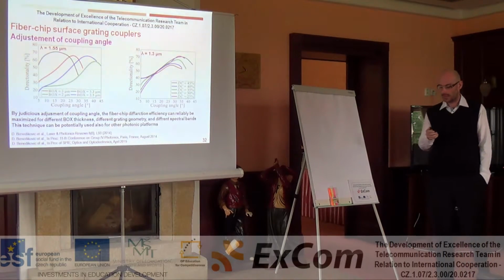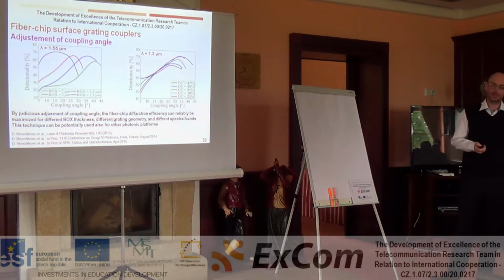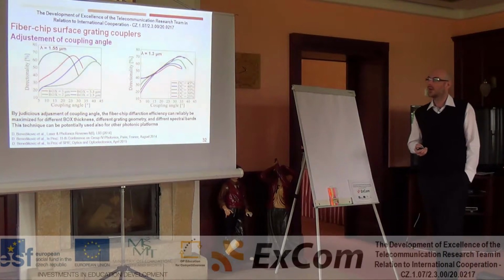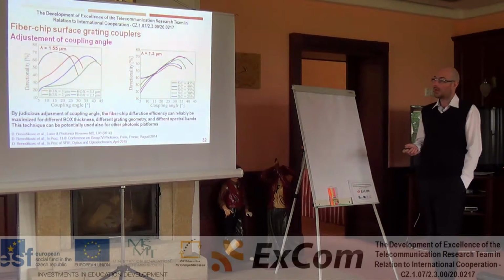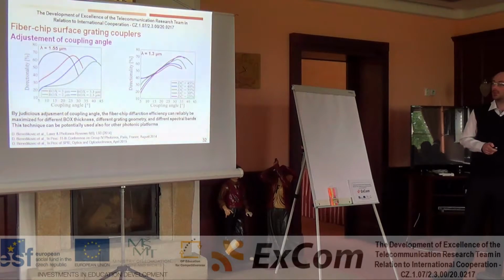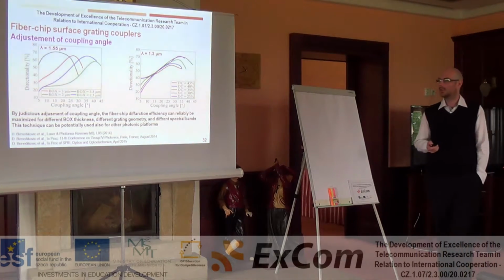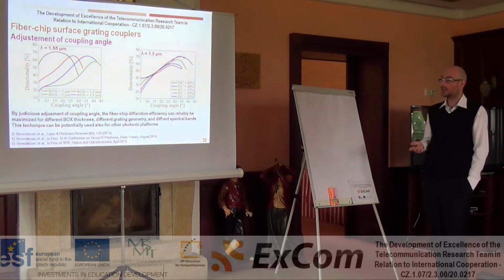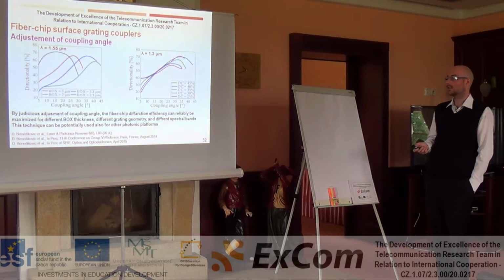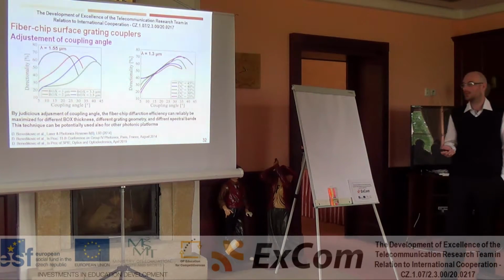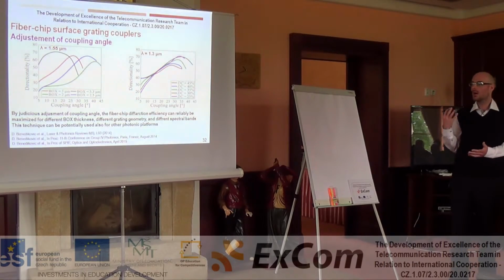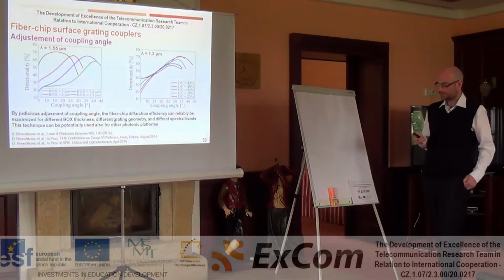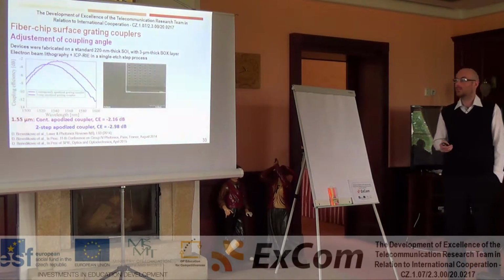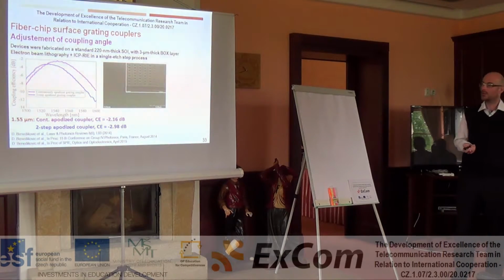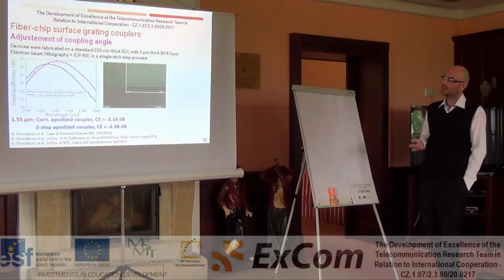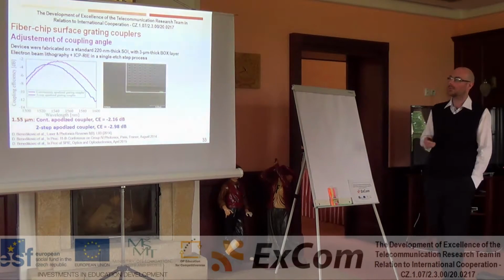This issue can be alleviated by optimization of grating coupling angle. By adjustment of coupling angle, the fiber chip diffraction efficiency can be readily maximized for arbitrary box thickness, different grating geometry, and also different spectral bands. We use this approach and we fabricated our grating couplers that provide very high coupling efficiency.